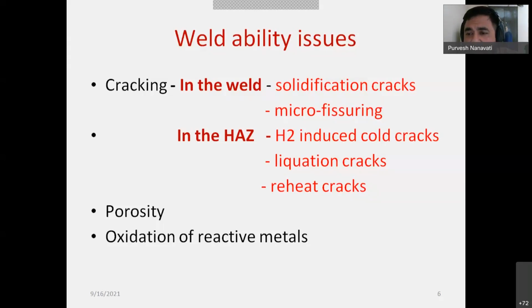Now liquefaction crack has something to do with a larger solidification temperature range, particularly in the fusion zone and the heat affected zone, right? And when there is a larger amount of low melting point eutectics under the contracting stresses, most of the time from the fusion zone and heat affected zone, there will be separation through a crack. So it's known as liquefaction cracks. And for liquefaction crack to occur, solidification temperature range is responsible. It means the higher the solidification range, the higher the liquefaction crack.